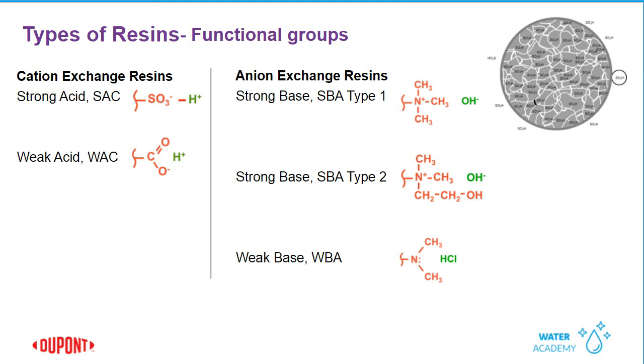The weak acid cation resin in industrial water applications is sometimes used in conjunction with the strong acid cation resin to improve chemical efficiency. This is in waters that have high hardness to total cation ratios. The weak acid cation resin can also be used alone in high TDS softening applications. Here it's used in the sodium form. When it's in this form, it will remove all hardness and not just that which is associated with alkalinity.